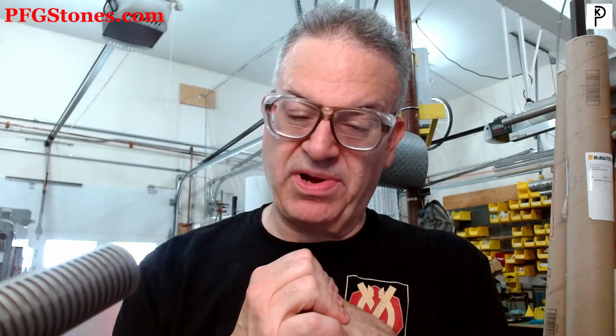So right now we could talk about three little pieces of grit: aluminum oxide, silicon carbide, and we talked about diamond. And of those, that's the order of hardness. Aluminum oxide has a certain hardness. Silicon carbide is harder. Diamond is way harder. We talked a little bit about chemical stuff. Aluminum oxide, grinding aluminum in the hot zone, there's going to be some chemical reaction going on there we don't want. On the other hand, diamond, grinding steel, is going to cause another chemical reaction we don't want.